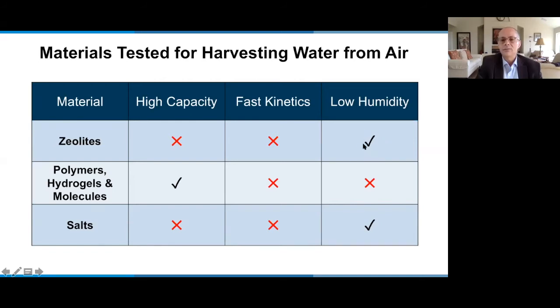So zeolites, they're very good, as you know. Desiccants are made, many of them, of zeolites. They love water, so they do take up water from low humidity, but they hold onto the water so tightly that you don't get fast kinetics, and they also suffer from lower capacity for water. Polymers and hydrogels and these molecular crystals, they're great at attracting water. They're very hygroscopic, but they don't have good kinetics, and they do not take up water from low humidity. They only work in humid regions. Salts, they're great at taking water from low humidity, as you know, hygroscopic salts, but they don't have high capacity. And again, you have strong interaction between the water and the salt, and therefore it's not easy to have fast kinetics.